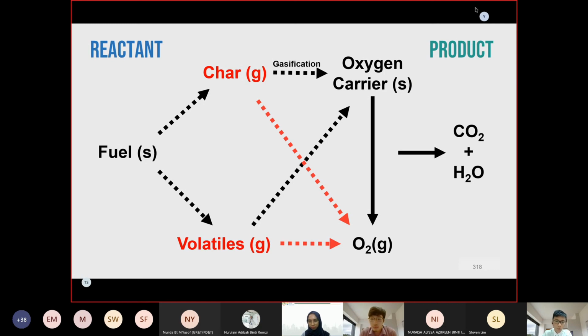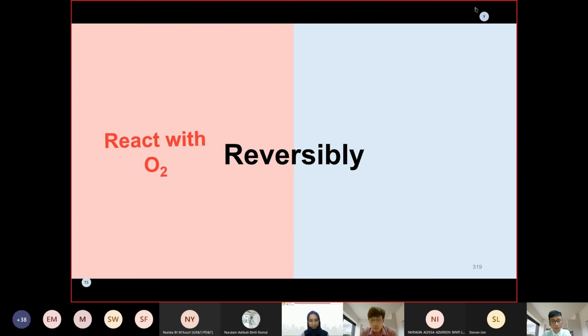That is only gaseous fuel combusted using the heterogeneous solid-gas reaction. In general, the OC for CLOU needs to have special characteristics and needs to react reversibly with the gas phase oxygen under high temperature. This places special thermodynamic and kinetic demands on the OC, which are not needed in CLC. The OC for CLOU must have the ability to react with oxygen from the air reactor and release this oxygen by decomposition in the fuel reactor.